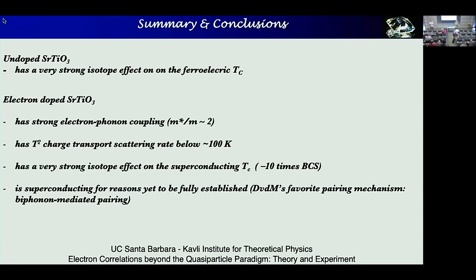Well, normally what happens in BCS theory is the TC is proportional to the phonon frequency, and then e to the power -1 over lambda. It turns out that the phonon frequency does not enter into the lambda. There's a compensation there that makes it independent of it. So it's only the prefactor. So making your material heavier means that the phonon frequency goes down. And so that sets the effect in the BCS model. And so that gives you an...